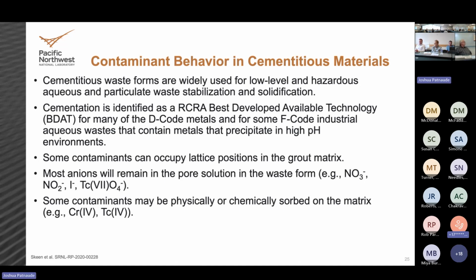We can also get that suppression by building in reduction mechanisms into the waste form by adding slag or adding iron or adding sulfur in. And this will also suppress the release of metal species and some redox sensitive radionuclides like technetium.